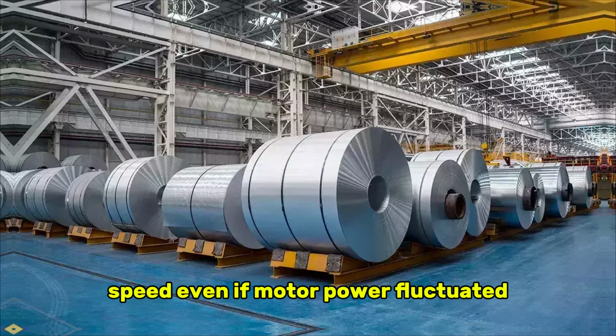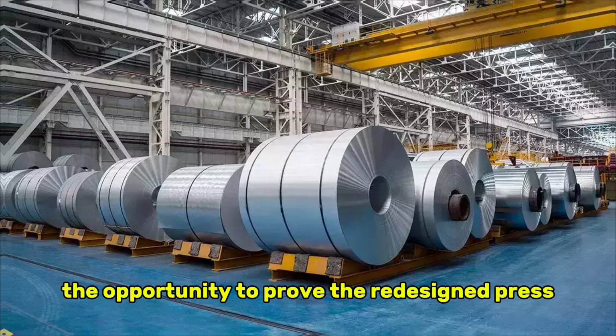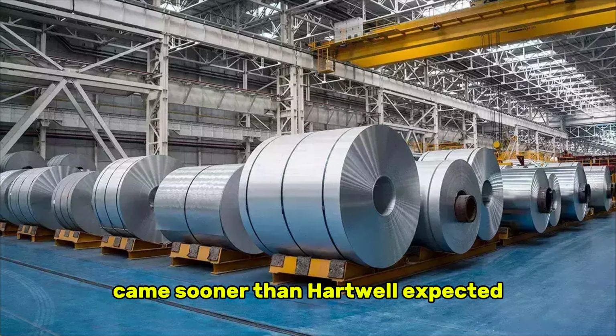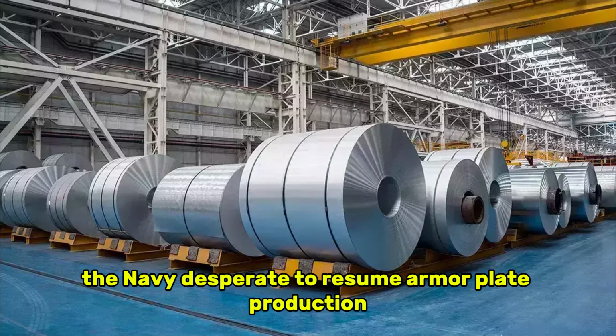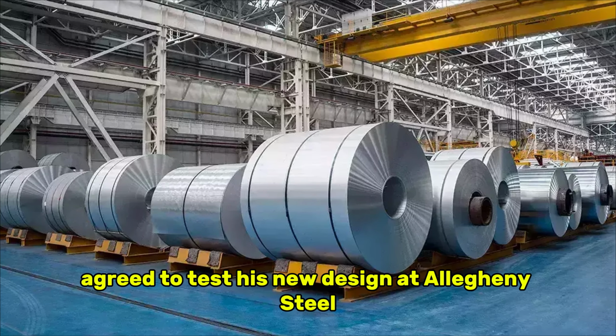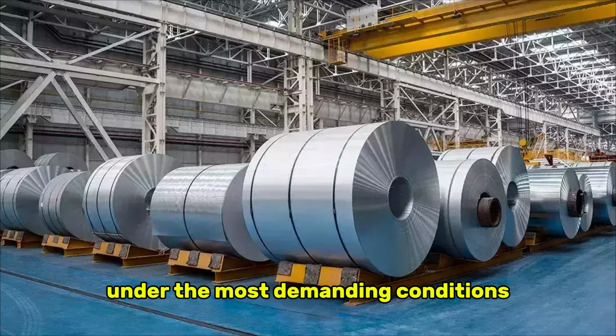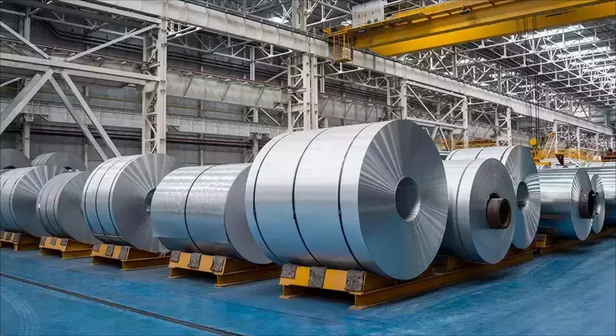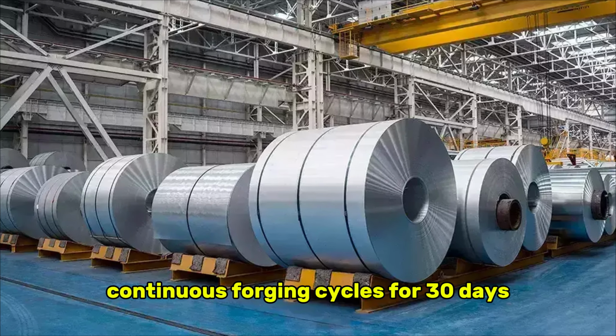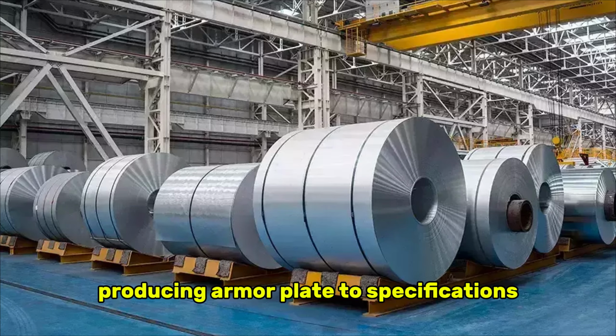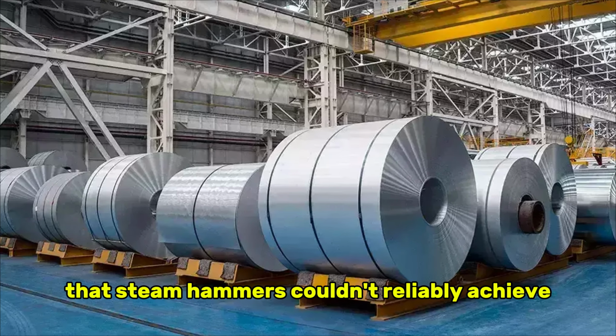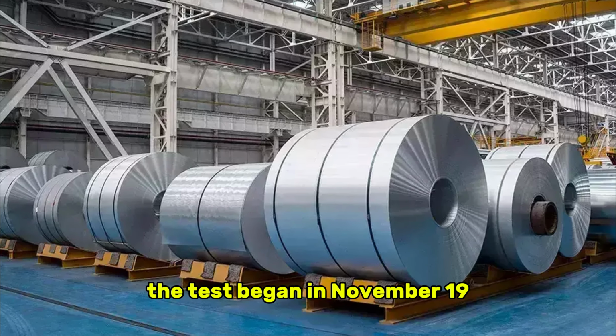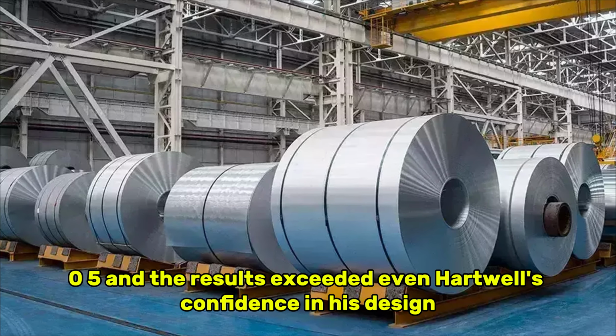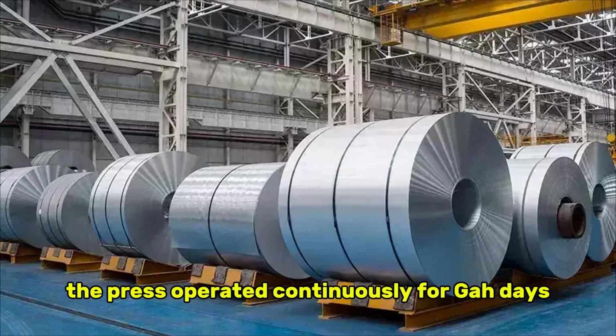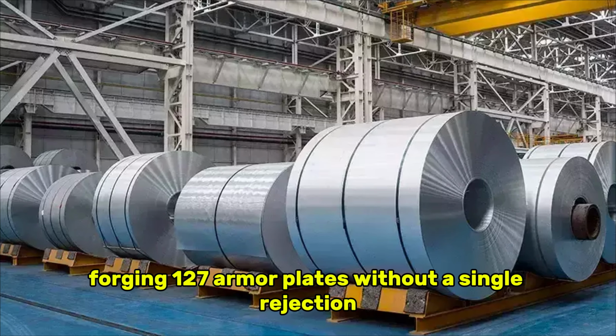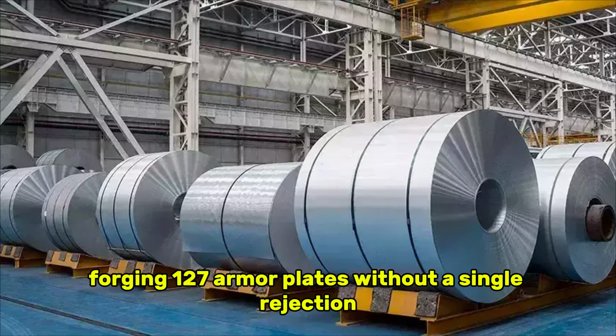The opportunity to prove the redesigned press came sooner than Hartwell expected. The Navy, desperate to resume armor plate production, agreed to test his new design at Allegheny Steel under the most demanding conditions: continuous forging cycles for 30 days, producing armor plate to specifications that steam hammers couldn't reliably achieve. The test began in November 1905, and the results exceeded even Hartwell's confidence in his design. The press operated continuously for days, forging 127 armor plates without a single rejection.